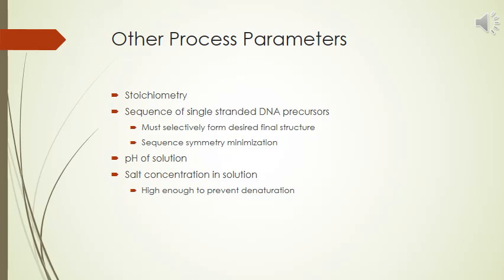Finally, since DNA is a charged molecule due to its negatively charged phosphate groups, the stability of the molecule depends strongly on the pH and salt concentration of the environment. If the salt concentration is too low, the electrostatic repulsion between phosphate groups will favor separation into single strands and duplexes will not form.